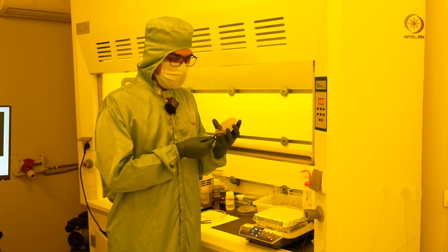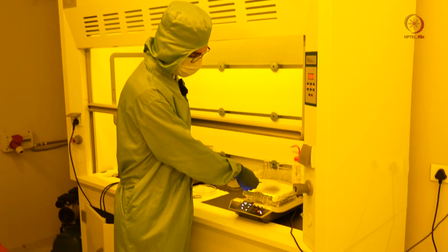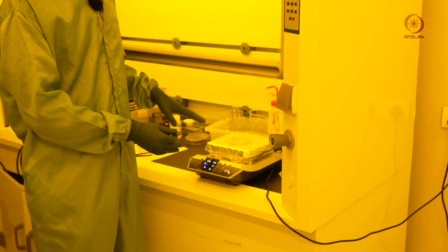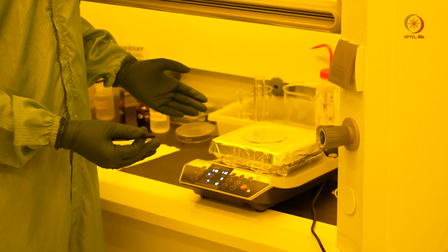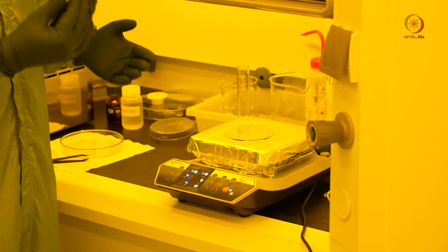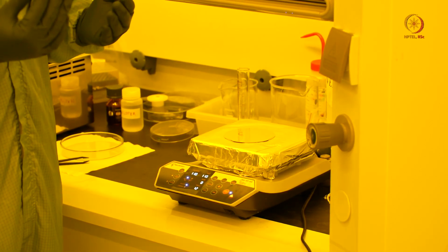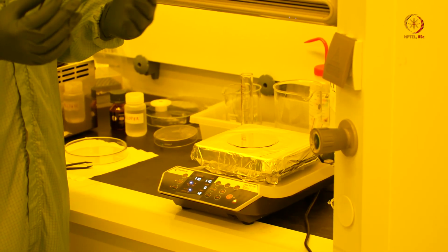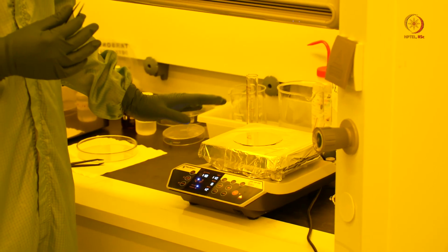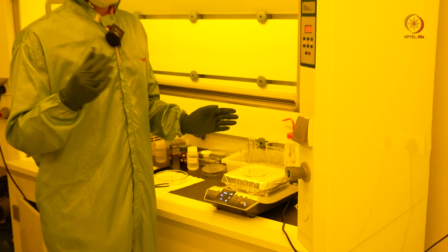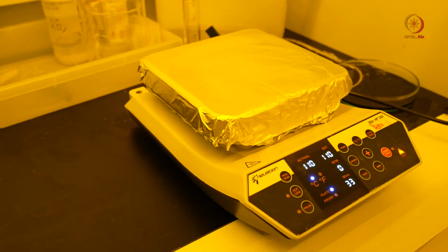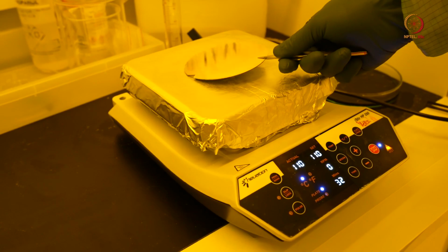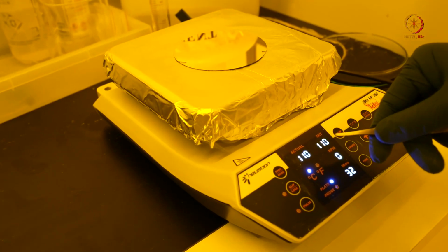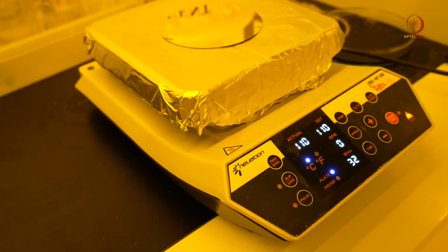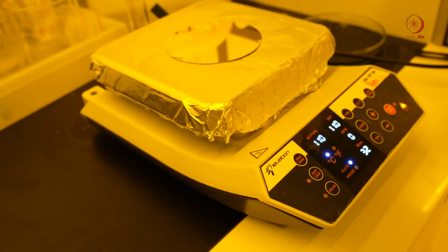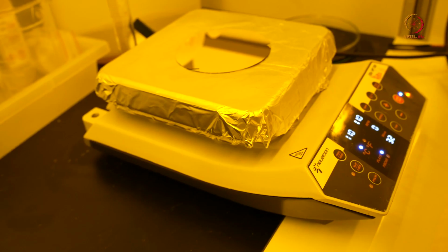So the dehydration step requires heating the sample on a hot plate at around 110 degrees Celsius for around 10 minutes. Okay, so anything more than 100 degrees Celsius is good, but we typically go for 110 degrees Celsius. Okay, so let us keep it here for 10 minutes and then we will continue the process. So we are going for the dehydration bake. So you can see the hot plate maintained at 110 degrees Celsius. So let us wait for 10 minutes so that the entire moisture on the surface of the wafer is gone, so that we can prepare it for lithography step.